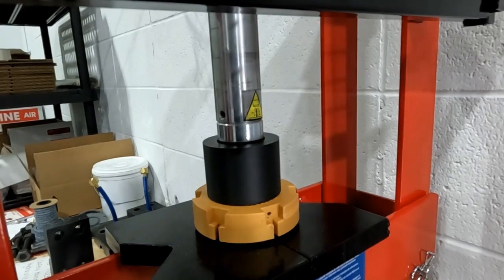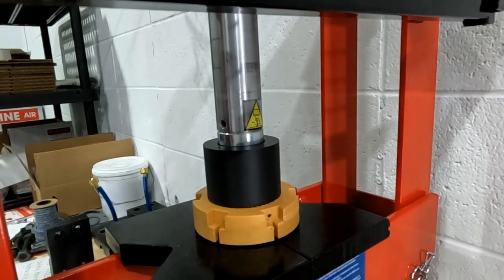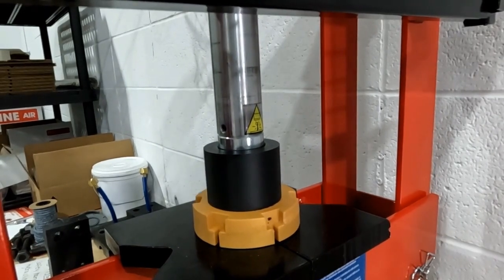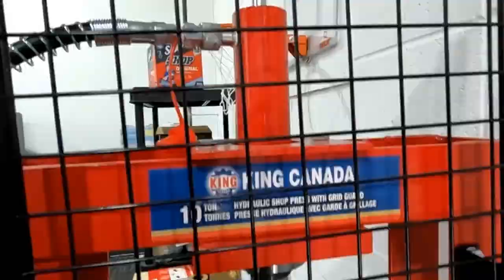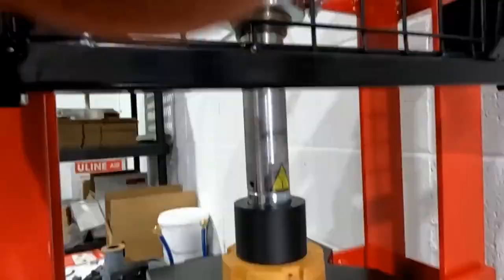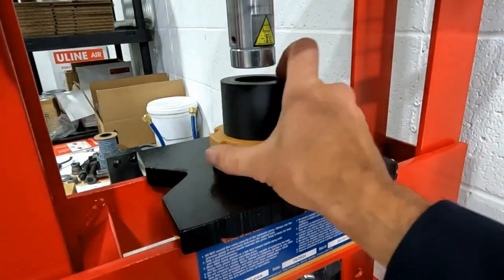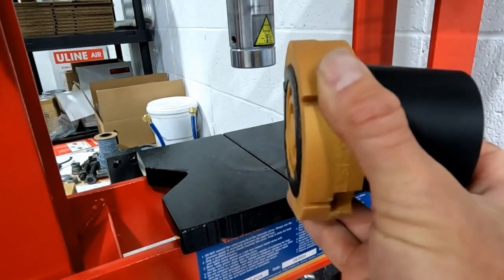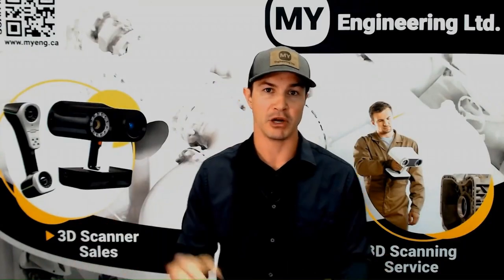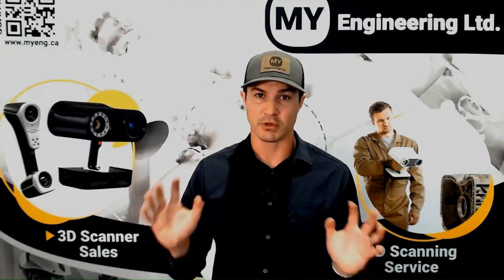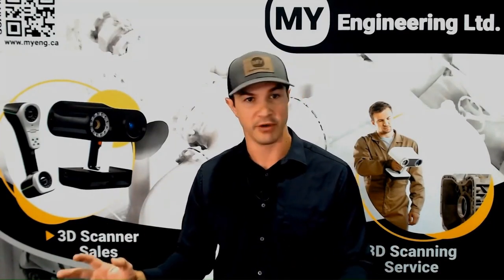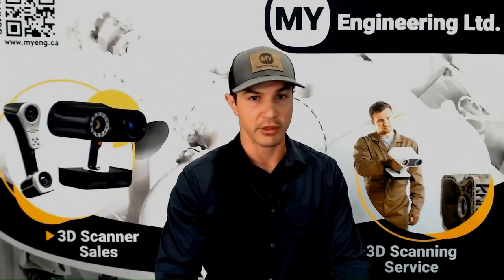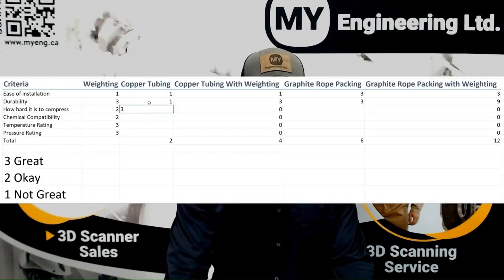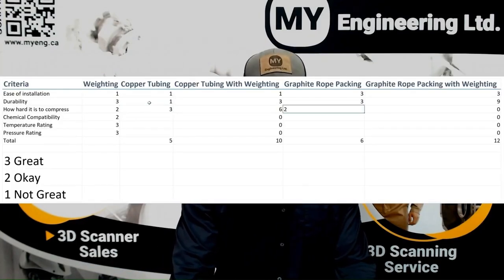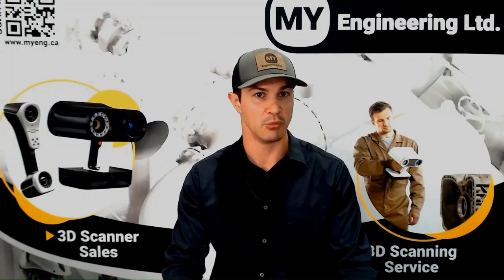Did the same test with the graphite rope packing, got up to over 5 tons before it got close to flush. But we have done other testing in the past, which has shown that it's almost impossible to take a standard 1/4 inch graphite rope packing ring and compress it to 50% of its initial height. It just won't go that far no matter how much force you put on it. The copper tubing was much easier to compress than the graphite rope packing. I'm going to give that one a 3 as the winner here, and I'm going to give the graphite rope packing a 2. It wasn't impossible, but it was somewhat difficult.